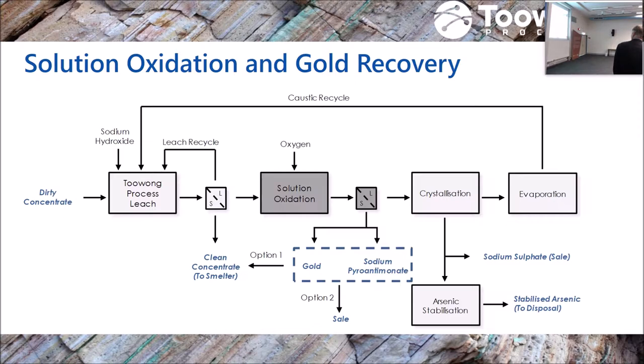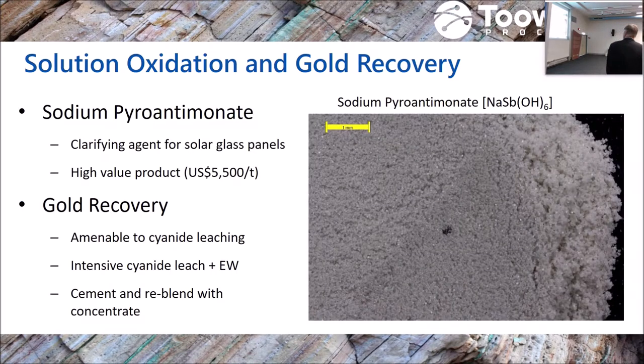So gold comes out here, a fine sludge, and if there's a lot of antimony, you'll basically produce a sodium pyroantimonate. So there's options there to deal with the gold, either blend it back in with the concentrate or treat it separately, but it's not lost. Next stage, so that's a bit of the sodium pyroantimonate. It's used as a fining agent in glass. So the solar cell industry is actually in demand for pyroantimonate. It's gone up quite a bit in the last 5 years. It basically makes the glass clearer. So the market is using a lot more of it than they did at first.